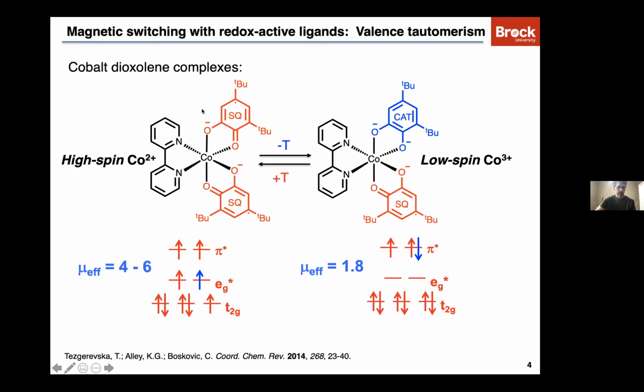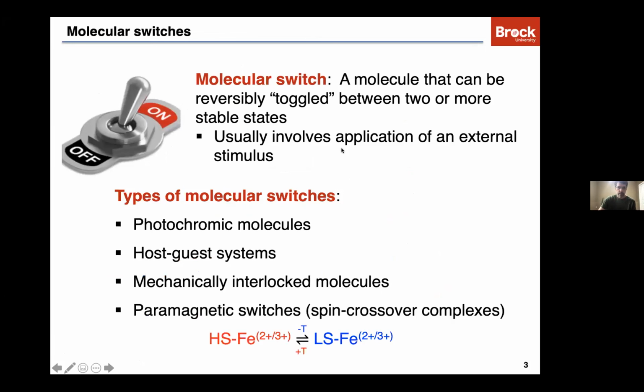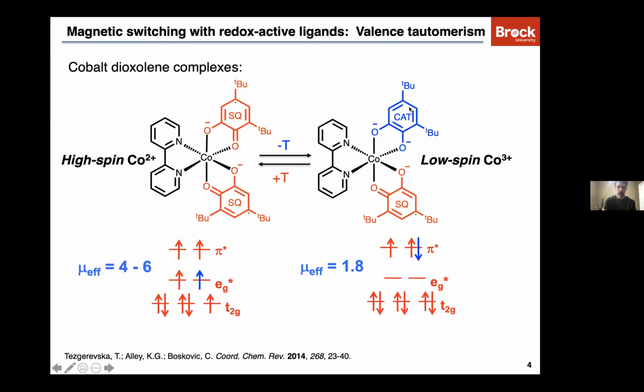And I probably don't really need to go through this with everyone, but the difference between the valence tautomers and the traditional spin crossover complexes is you also have an electron transfer. So you have change of spin state at the metal center, and electron transfer from metal to ligand. In this case, you produce the coordinated catecholate and semiquinone with a low spin cobalt-3 as a low temperature isomer.